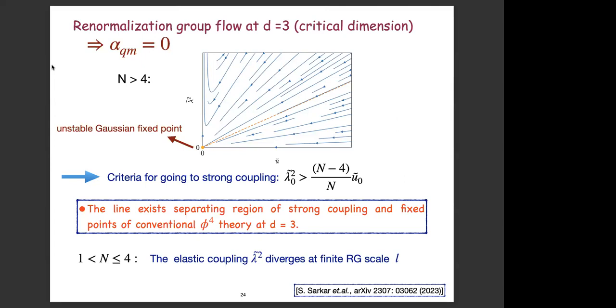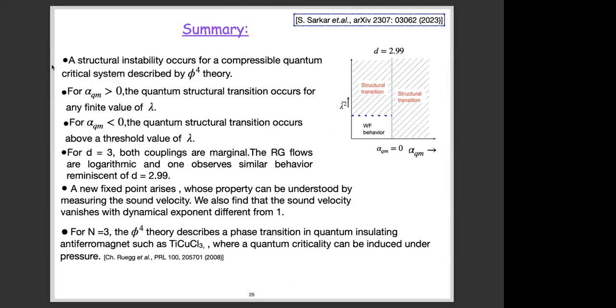Okay, with this I will conclude and give you the summary. What we saw is that for our case, structural instability occurs for this compressible quantum critical system described by phi-four theory. We have, for alpha quantum greater than 0, a quantum structural transition for any finite value of lambda, as shown in this plot here. But for alpha quantum less than 0, we have Wilson-Fisher behavior, and above a threshold value of lambda, that is, above the separatrix that we saw earlier, there is a structural transition again, which is quite different from the classical critical system, I guess.